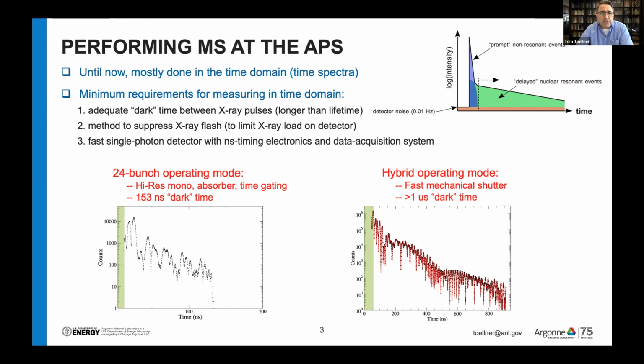So the minimum requirements you need to do these sort of measurements are, you need an adequate amount of dark time between the pulses. By adequate, I mean the time should be basically a nuclear lifetime, but preferably longer. And then you need a method to suppress the X-ray flash, and then you need a fast single photon detector and detection system to carry out the timing to construct a time spectrum.